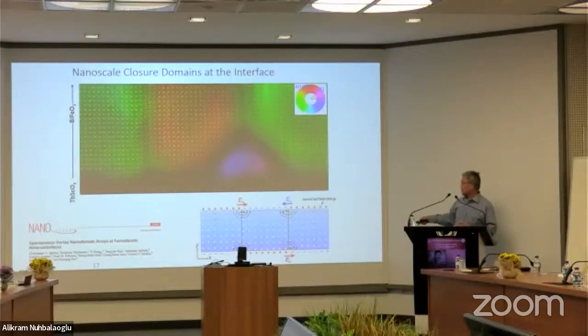It's very straightforward from a simple physics perspective, and we can get this kind of picture. So polarization in a ferroelectric material, we have a bound charge. It starts with a negative charge, a positive charge on the other hand, and then they line up. So when this moment accumulates at the surface or interface, you have a negative charge on this side, positive charge on the top side. This charge is called bound charge. So it doesn't move itself, it's attached to the structure. And then the polarization is pointing downward. You have a positive charge here, negative charge there.